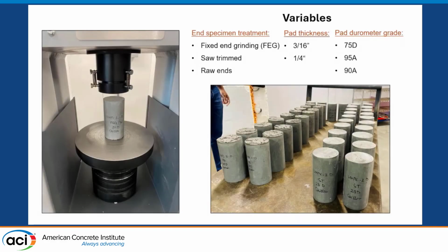A lot of work. The variables which we changed within this experiment were the end condition of the cylinder. So if we ground it, if we saw trimmed it, or if we left it raw. We changed the thickness of the pad between 3/16 and 1/4 inch. And then we also changed the hardness of the pad.